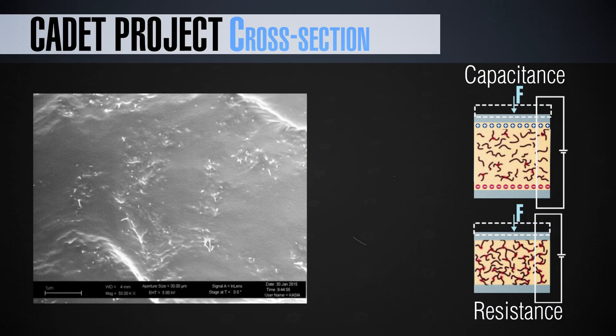If the interface is inadequate, the sensor response would be below our requirements. From the sketch on the right, you can see what happens when you apply pressure: both the capacitive and resistive components vary. The variation of the capacitive component is connected to the change in thickness of the insulating PDMS part, while the variation of the resistive component is connected to the increase or decrease of contact points between the conductive fillers as pressure is applied or removed. Monitoring both components in the impedance measurement greatly increases the sensitivity of the sensor.